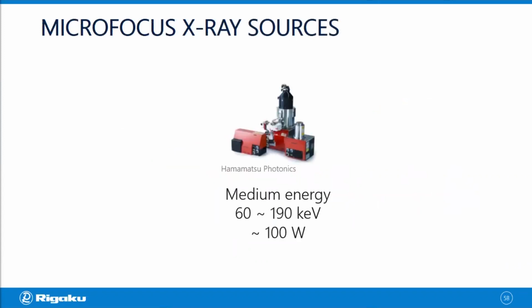For the X-ray source, to achieve high resolution, usually people use microfocus X-ray sources with a tiny X-ray spot. And the most commonly used X-ray sources fall into this category. It's a medium energy, 60 to 190 kV energy range, and its power is 10 to about 100 watts. And this is the category of X-ray sources that are most commonly used for X-ray CT. And it covers a wide area.